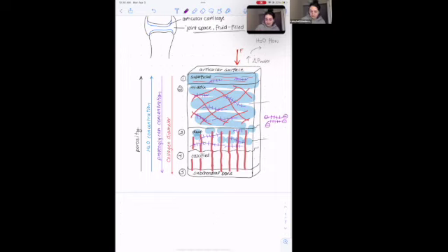And that continues down into the deep layer where you have that higher concentration of proteoglycans, so you're getting more resistance to compressive forces. And then this calcified layer, the fourth part, is really there to transition into the bone. So it has some calcification in the same way that the bone below has a lot of mineralization, and it still retains some of those cartilage-like features so that it transitions and you don't get delamination of two completely different layers next to each other. Or cracking, that's a place where cracking can occur as well.